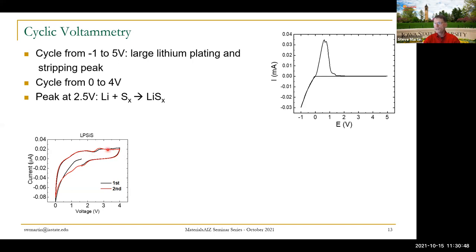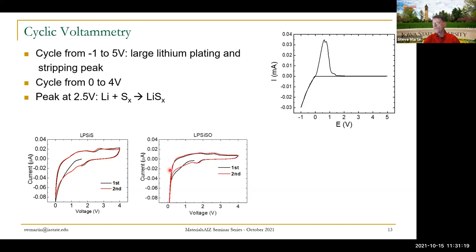And you can see at a 1,000-fold increase in scale, we do see a little bit of chemistry, which we think is associated with some of these sulfide sulfur forms. Remember, sulfur is about a 3-volt cathode. So it's not too surprising in the pure sulfide glass that we get a little bit of chemistry going on there. Most of the sulfur is sulfide, but some sulfur is probably in the reduced pure sulfur form, and we get some current out of that. When we go to the oxysulfide now, you see we've narrowed that window up a lot. Maybe that oxygen is going in and oxidizing that sulfur and eliminating it.